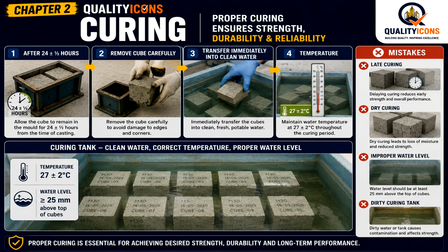The next step is very important, curing. Please remember this point. Concrete is equal to a born baby. Proper curing ensures strength, durability, and reliability. After 24 plus or minus half an hour, carefully remove the cubes from the mold. Immediately transfer them into clean curing water.